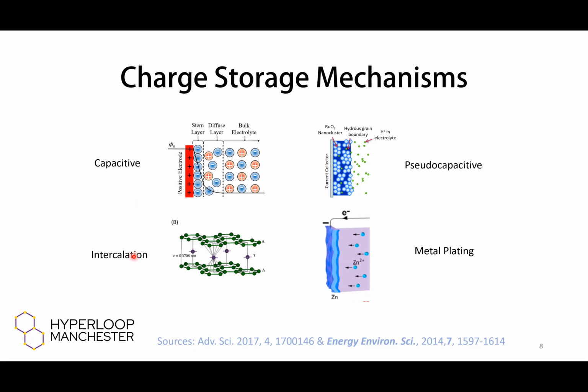Then there's an intercalation type charge storage. Now, this is actually one of the building blocks of lithium-ion batteries. In the middle here, you can see lithium ions, which are sitting in between graphite rings or graphite sheets. This is where lithium has entered from an external surface and then penetrated into the material and started to become stable within its structure. Not many materials and many elements can do this, but the ones that can accept lithium inside.